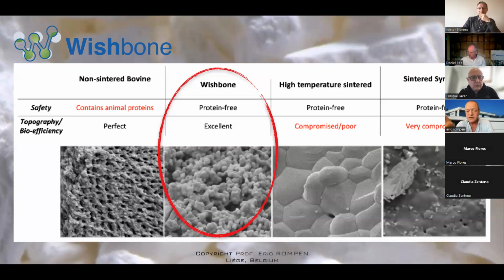The other hydroxyapatites on the market, which are the most common, because the simplest way to eliminate the proteins is just to heat the material at 1000 degrees. Then those materials are really protein-free, so very safe, but then the topography is really compromised, and the bioefficiency is highly decreased. And that's the problem. On the market at the moment, what we have is either sintered hydroxyapatites from bovine origin, which are very safe, but their bioefficiency is low, or, on the other side, the non-sintered bovine, the BioOss, which is very osteoconductive, with a nice topography, but not the safest process. Next slide, please, Daniel.